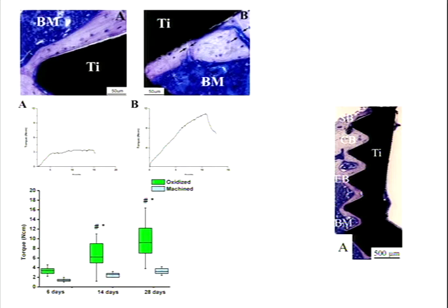It means that where we have a higher expression of bone formation and bone resorption, we have a higher degree of stability during the development of osseointegration. And this is important because it links what happens on the cellular level with what we can demonstrate using tools which are relevant for the clinical situation.